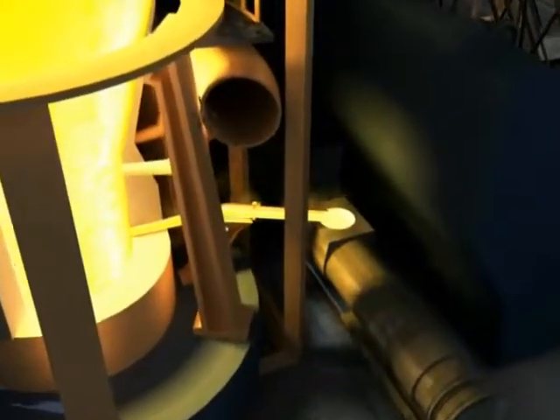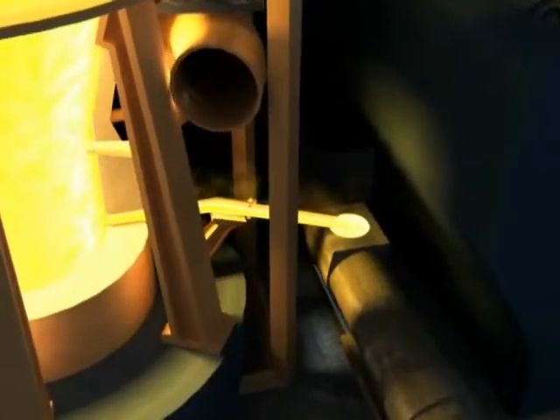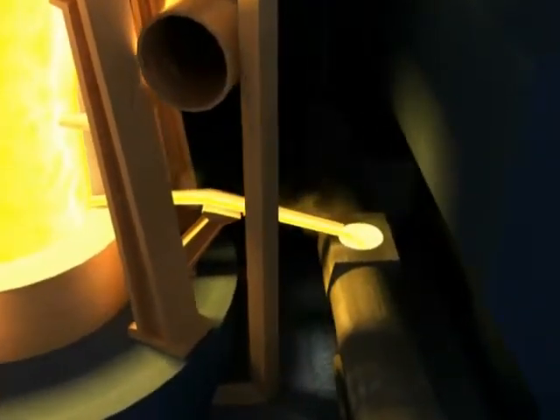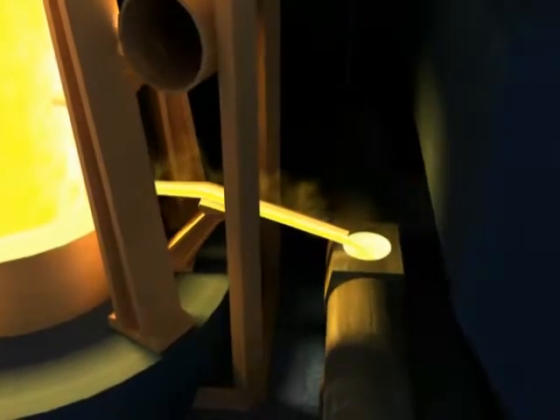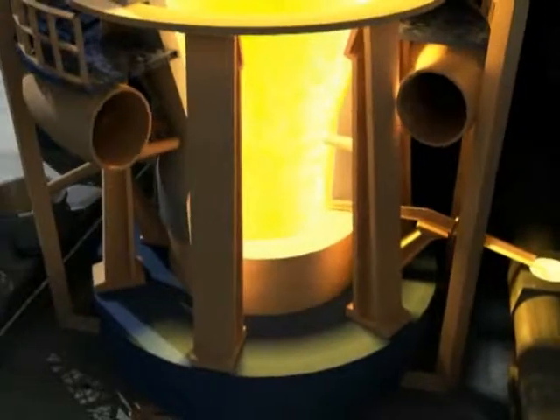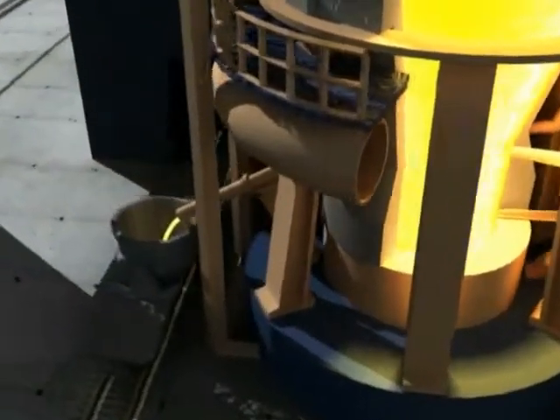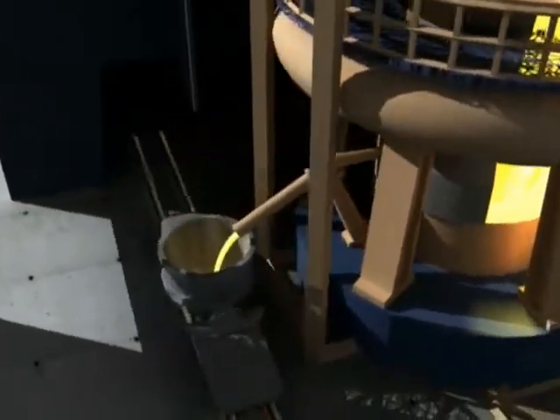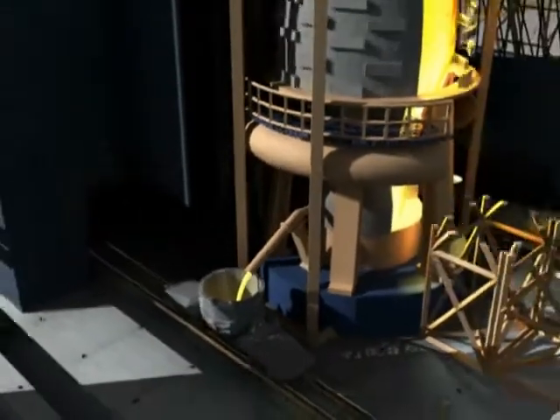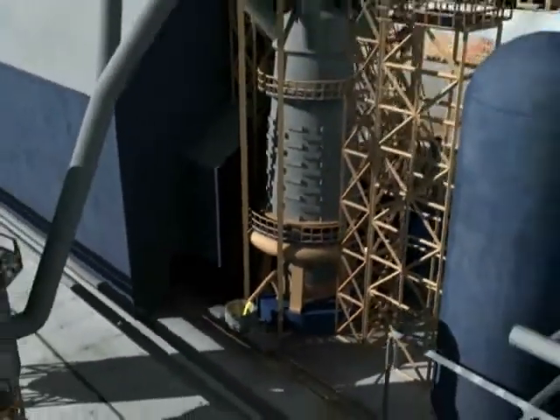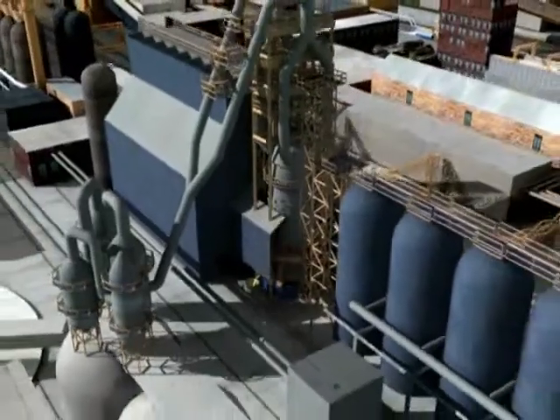Hot metal is tapped from the furnace on average 15 times a day. It is poured into the so-called torpedo cars and sent to the BOF and EAF steel smelting plants. In the meantime, slag is poured into slag cars, which are sent to slag processing units. The total capacity of MMK's blast furnaces is about 10 million TPY of hot metal.